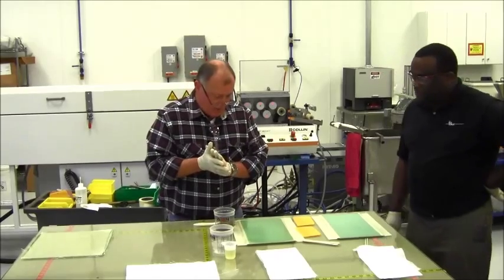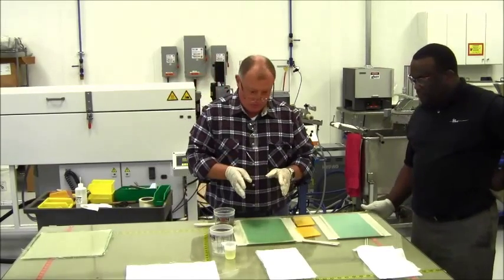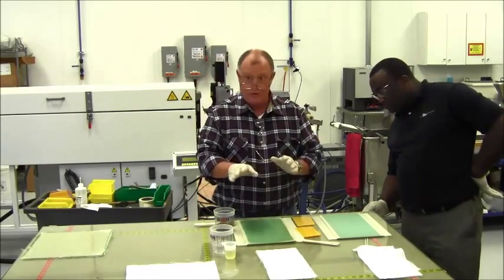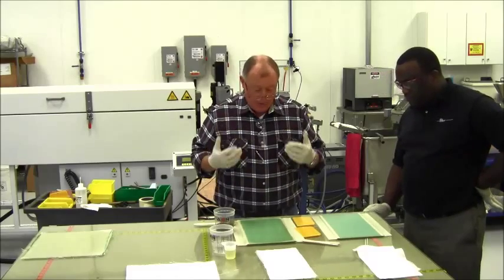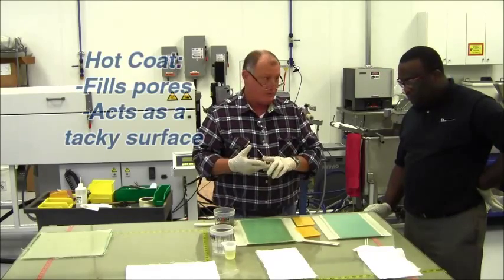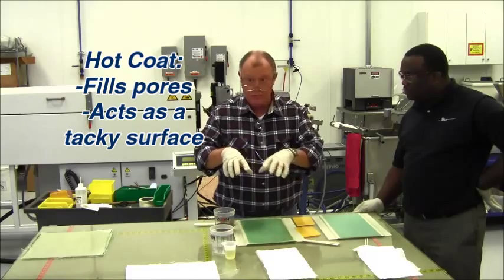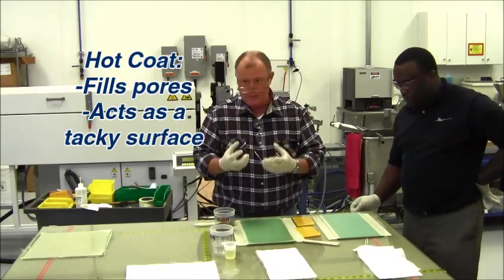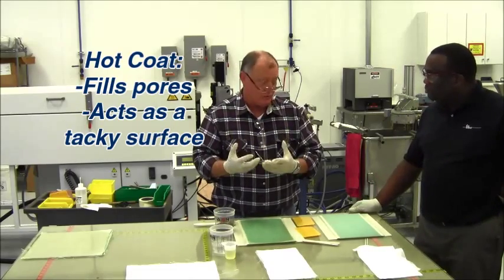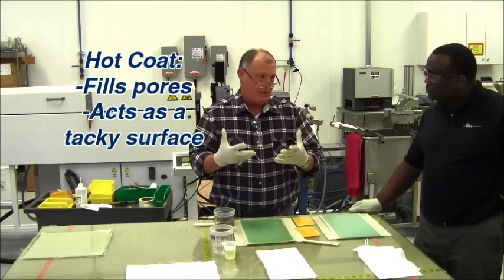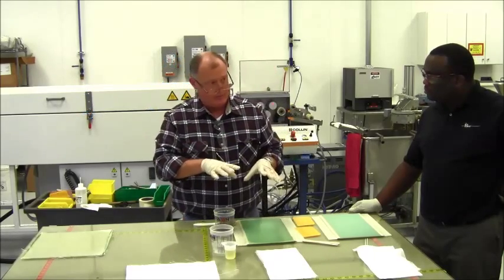Okay, we've got the core material already coated with a hot coat. That hot coat's going to do a couple things. It's going to fill pores in the foam, so it doesn't try to pull resin out of our fabric going down on the foam. And it acts as a tacky coat to hold Innegra fabric down.